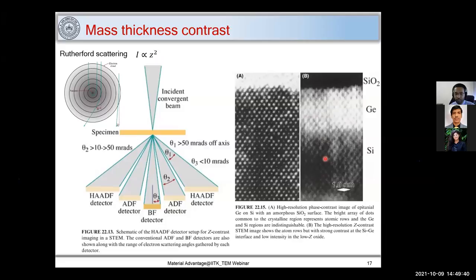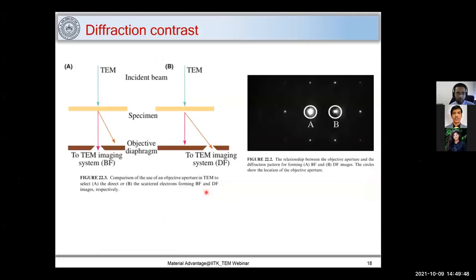That is how we can use the HAADF detector to find out the composition in a given specimen. So with this, we'll move ahead and talk about diffraction contrast. We talked about mass thickness contrast and diffraction contrast, and these are all amplitude contrast. So here I have shown an image where the electron beam falls and there will be a diffraction phenomenon which is occurring. So I consider only a transmitted beam, and that I call bright field imaging.